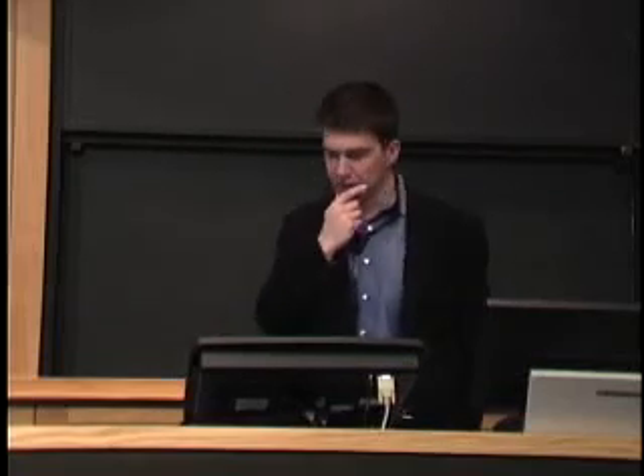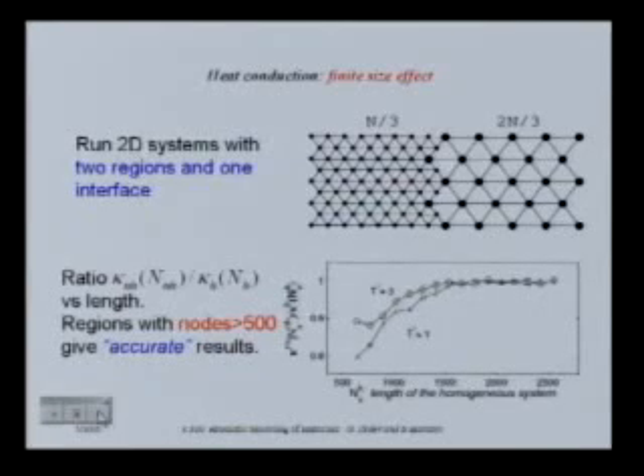But here it gets more interesting. If you look at heat conduction through a coarse-grained interface—let's say you're fine on this side, these are atoms, and here we've removed a bunch of nodes, we've coarse-grained—you look at the heat conduction through this. So you set up a temperature gradient and essentially look at the heat flux when you do dynamics.